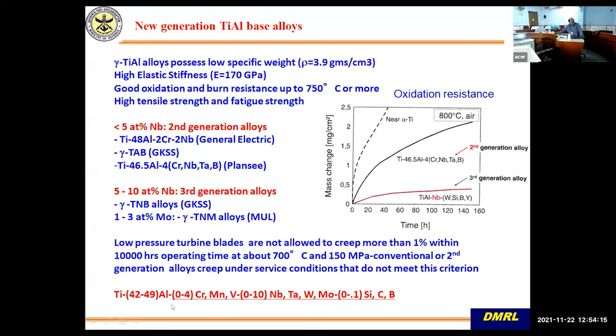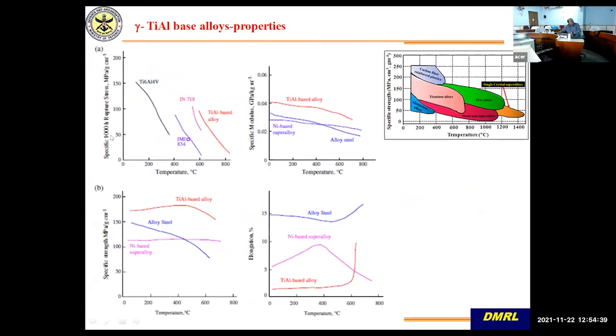So there is also a design criteria for how you can decide what elements to add, slightly complex, but anyway. When you compare the oxidation resistance at 800 degrees centigrade, you can see the near alpha titanium alloys have got poorer oxidation resistance. The second generation has got better, and the third generation of gamma aluminides has got still better oxidation resistance. Here I'm showing you the properties of why gamma aluminides are attractive: specific strength, that is strength in MPa divided by density, as a function of temperature. You can see it surpasses the near alpha titanium as well as iron based alloys. Then specific modulus, much better as a function of temperature. Specific strength as a function of temperature, gamma aluminides are much better as compared to nickel alloy steel.